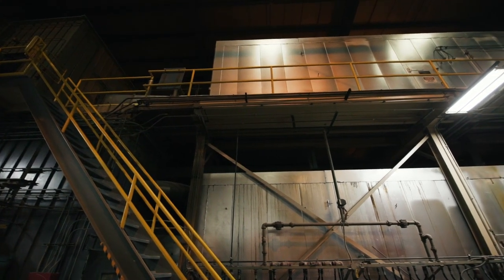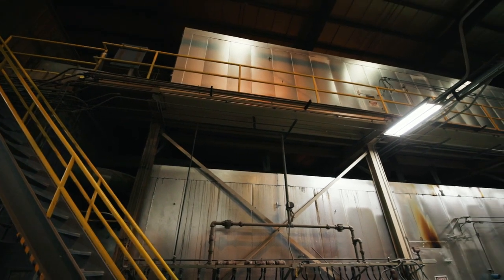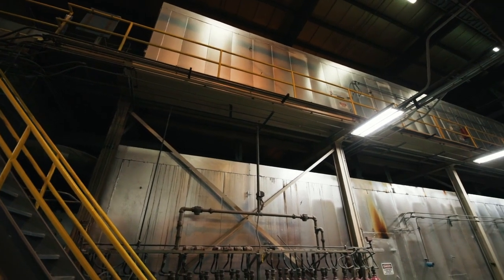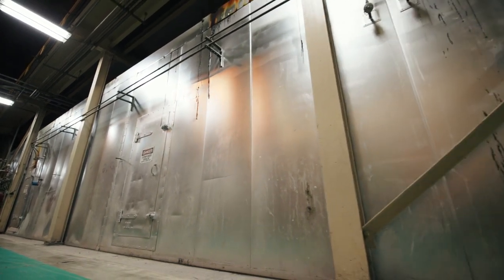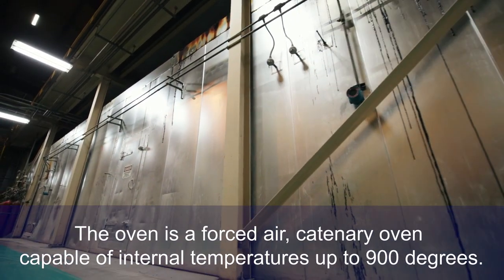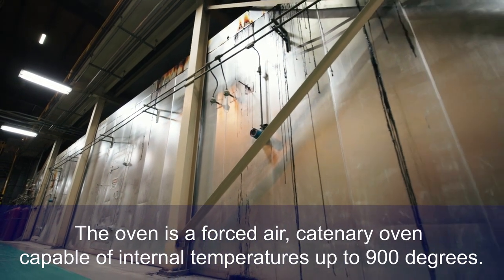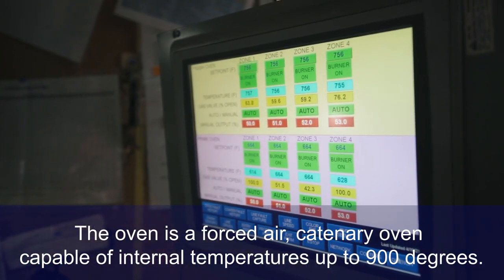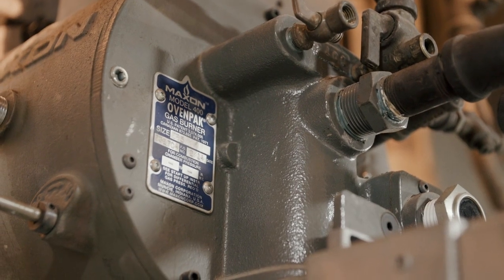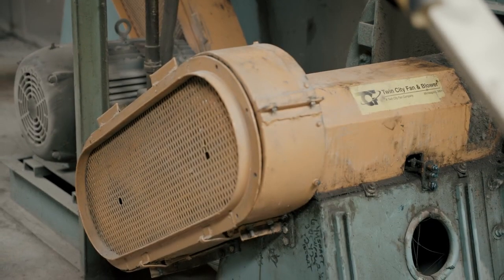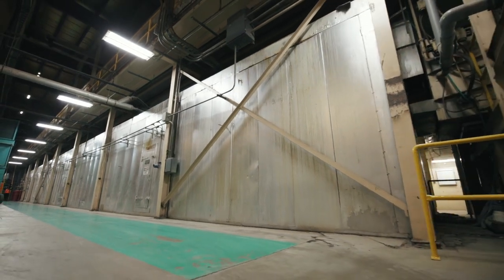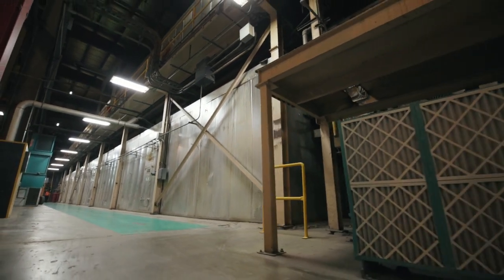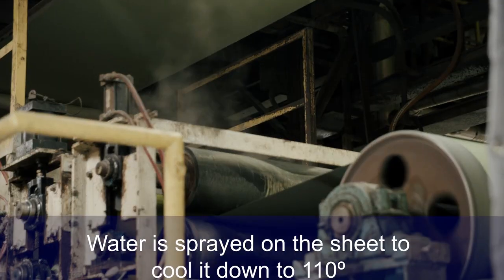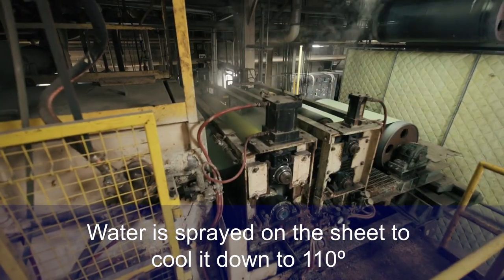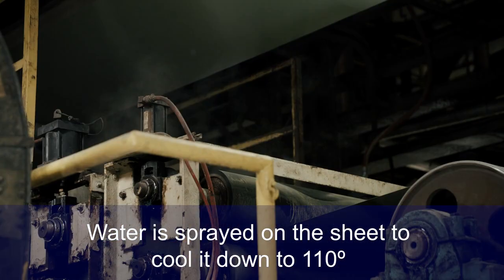Immediately after the sheet is painted, it enters the 125-foot long prime oven. Here we are flash drying the primer to the desired level of cure per the paint vendor's instructions. The oven is a forced air catenary oven capable of internal temperatures up to 900 degrees. To dry the paint properly, the metal must be heated to a peak metal temperature specified by the paint vendor for each specific paint. As the sheet exits the oven, it goes through a short cooling tank. Here we spray water on the sheet to cool it down to around 110 degrees before it continues to the finish coater.